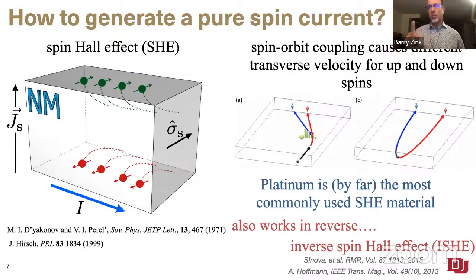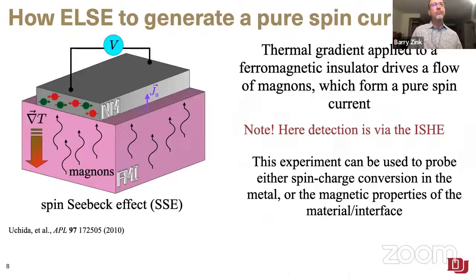And as I said, platinum is by far the most commonly used spin Hall effect material or spin conversion material in all of the experiments done to date, although there's lots of new ideas and exciting stuff of people trying to find other things. And that's basically what we'll talk about when we talk about chromium here in a minute, because in certain circumstances, it actually could be a nice replacement for platinum in some of these experiments. But before we get there, I want to introduce one other effect, and that's another way to generate pure spin currents, and that's by applying a thermal gradient.